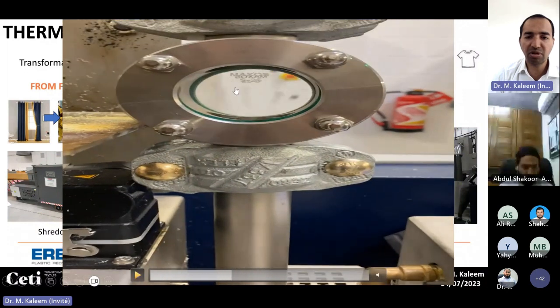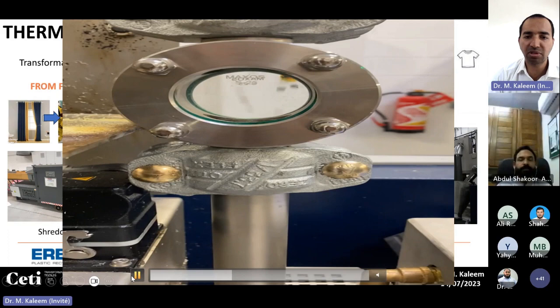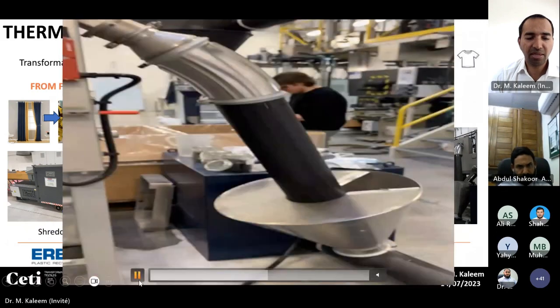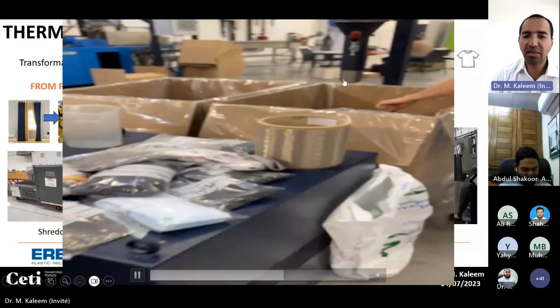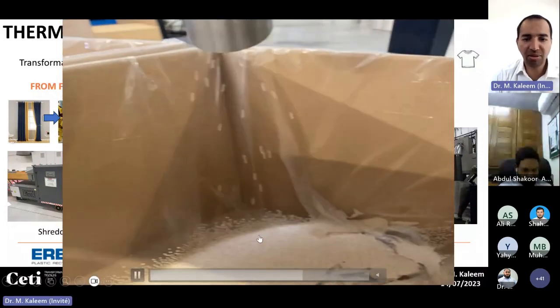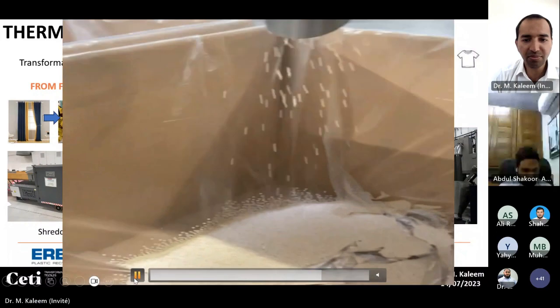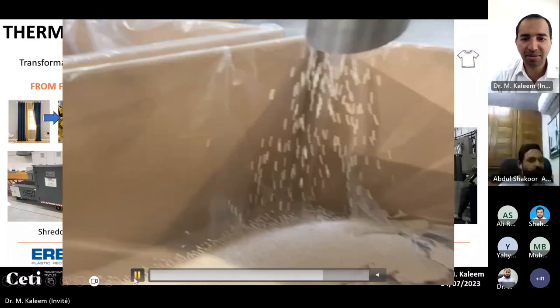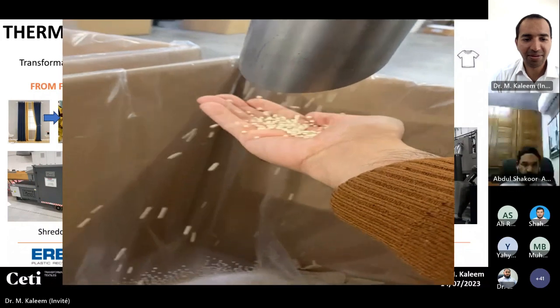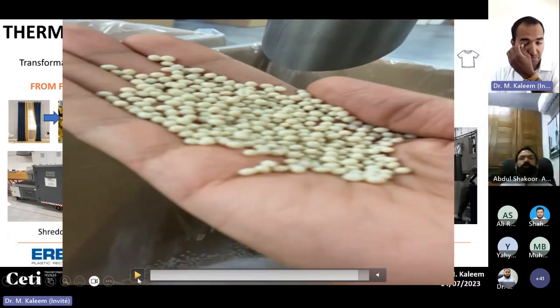And then at the end, you get the pellets. This is a water collection system. The melt stream is transferred into pellets. There is a cutter here, and at the end the pellets are collected by the water. And then here you have a dryer that removes all the water from the pellets and separates and dries them. At the end you get the pellets out of this material. So here you have recycled PET pellets.